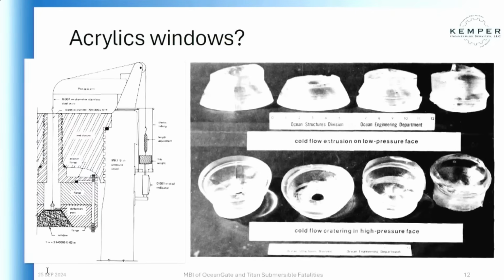And if you're putting it in a conical frustum, that looks exactly like an extrusion die for metal, where you take a billet and shove it through a big hole that goes to a small hole and you get a wire. That's the same thing that's happening with the acrylic, which is why you have to design that acrylic to be massive enough with the right shape to resist that effect, and you monitor for it. This is from one of Jerry's papers, where he tested a failure, and he demonstrated this failure reliably happens under these conditions. And those became the conditions that he made sure were not near the line.